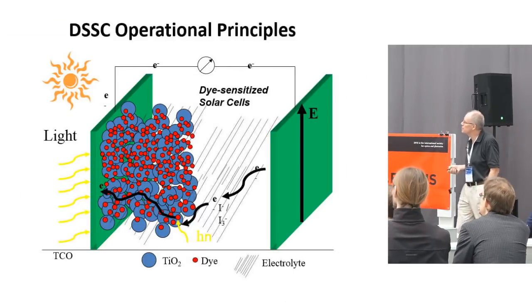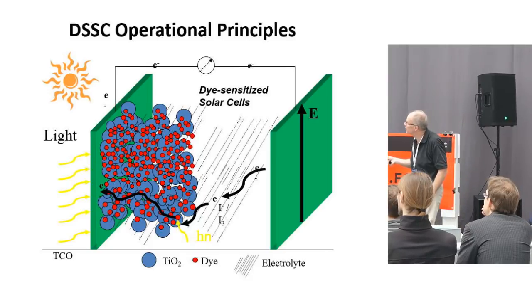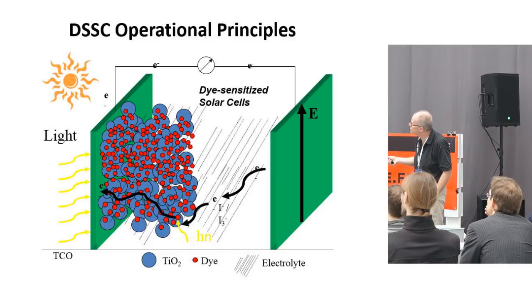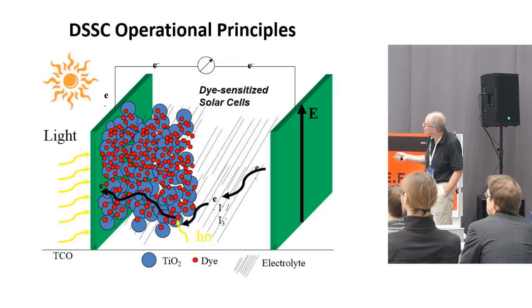Here is the process a bit. We have this pore system. You have the dye molecules on the surface. You shine light on it. You excite the dye, and the electron is injected into the TiO2. And it goes through all these particles to the contact, to do electrical work. It goes to the cathode, where you reduce the electrolyte, in this case I3- to I-, and then the electron is brought back to the oxidized dye, and you close the circuit.